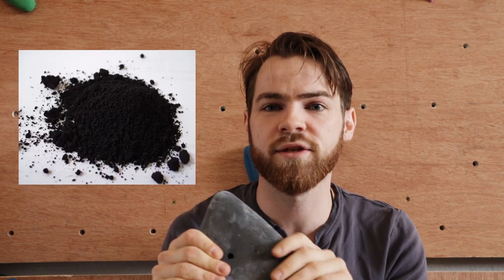You get a lot of grey holds out of this. They can give quite a nice aesthetic, but we've also been playing with black staining — carbon black added to the concrete. You have to add quite a lot: for a five to ten kilo pour, maybe 100 grams of carbon black, which can add quite a lot to the cost. They look really cool, but as soon as you get chalk on them, they go grey anyway. Probably the best way is to paint them with acrylics afterwards in the areas you're not going to be touching, to identify sets of holds for routes.